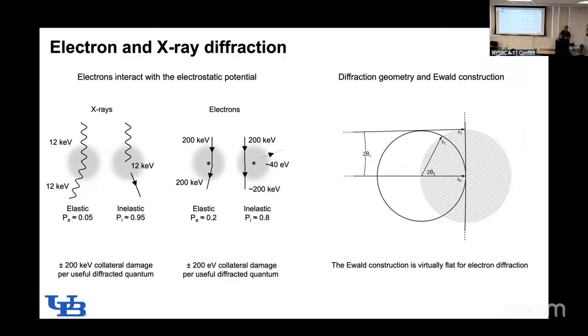Another advantage is that for every elastic event of electrons, there are fewer inelastic events than with X-ray, and they theoretically deposit less damage. I'm not sure if I believe this. I cite this paper all of the time, but in theory, for the same number of quanta in versus quanta out, you should have a better ratio of elastic to inelastic scattering, less energy deposited, and less radiation damage, at least in theory.